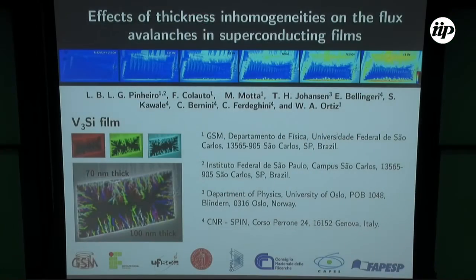Our motivation is that in some cases, we cannot build a device directly on a flat surface. Sometimes, for example, as in radio frequency cavities for accelerators, we want to deposit superconducting films in a complex shape. So different thickness gradients and different thicknesses around devices are expected. We want to understand the effect of this thickness gradient, not only in the smooth penetration, as we can see in the sequence of images on the top of the poster, but also in the avalanche regimes. If you want to discuss more about this subject, please come to my poster. Thank you.